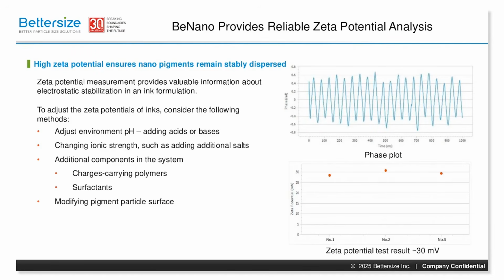The BeNano provides reliable zeta potential analysis, crucial for keeping pigment stably dispersed in inks. Here, we have a phase plot on the upper right and corresponding results down here from a nanopigment ink sample. This sample is a complex mix of nano-sized pigments. The measured zeta potential of around 30 millivolts shows BeNano's precision even with complex ink formulations.